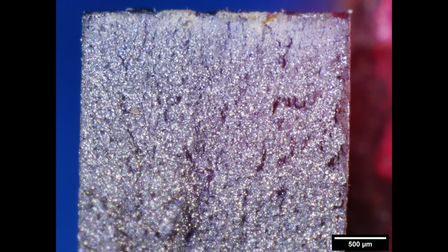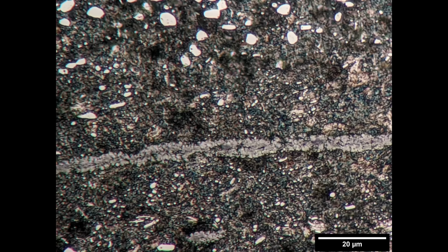And when we did the microscopy where we etched it, we saw these black dark regions with what are called lamellae in there, which indicates a pearlite structure. Pearlite is what happens when you cool the steel too slowly. Like if you cooled it in air, it would basically be all pearlite rather than martensite. So we don't want pearlite. It is soft and it's even somewhat brittle. So you get a bad microstructure for a knife.